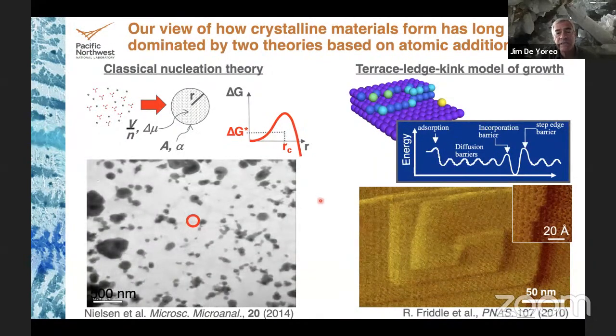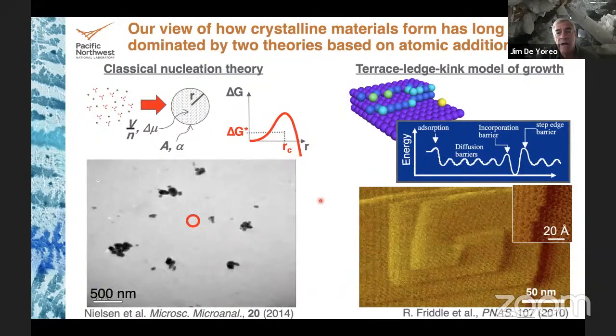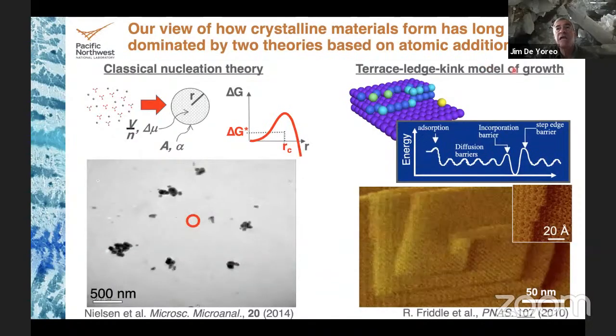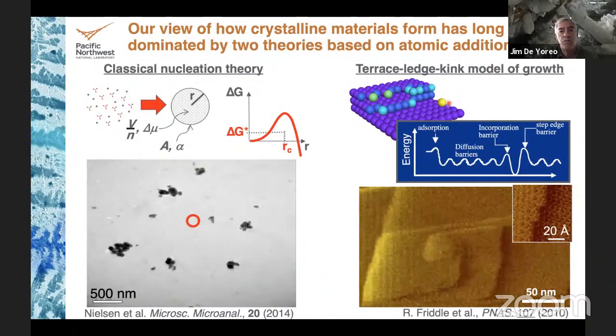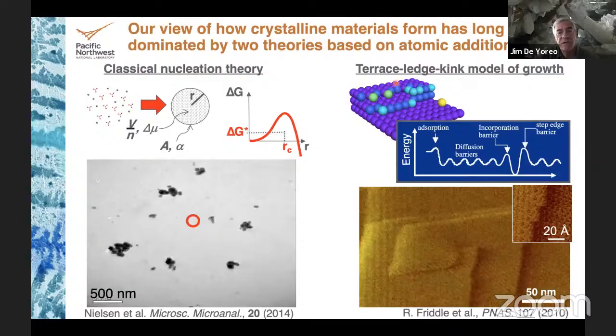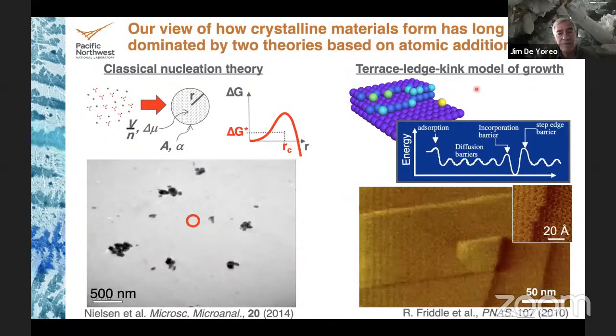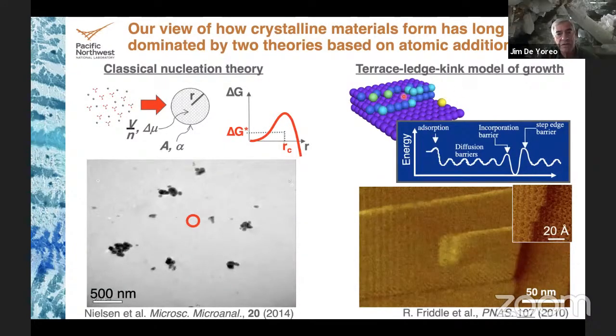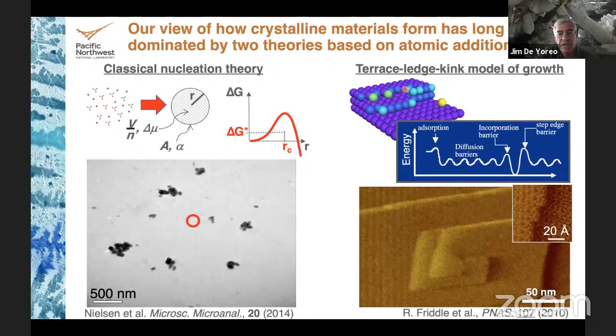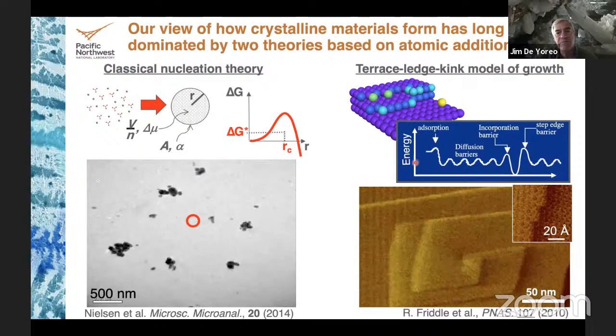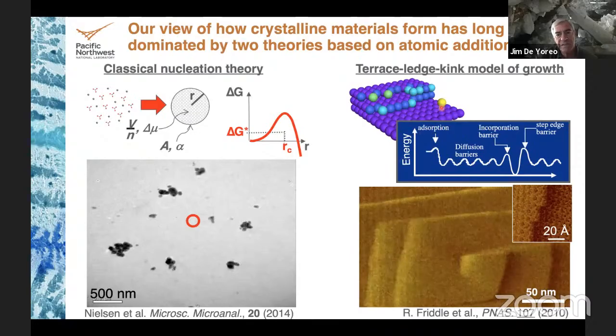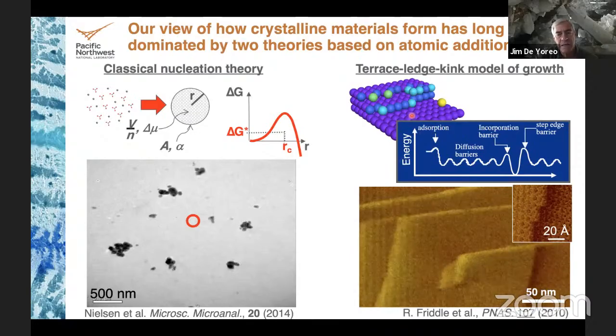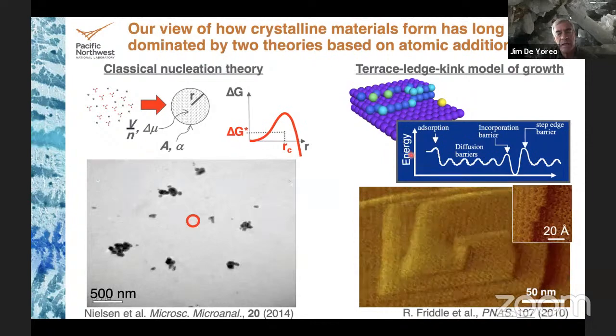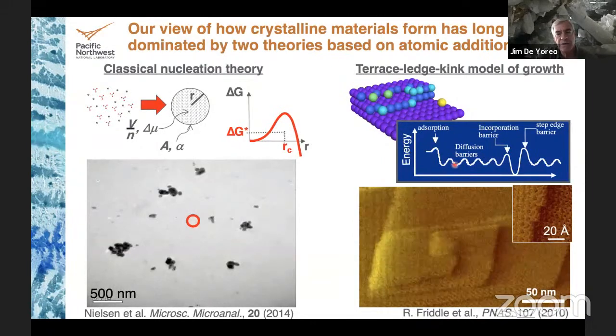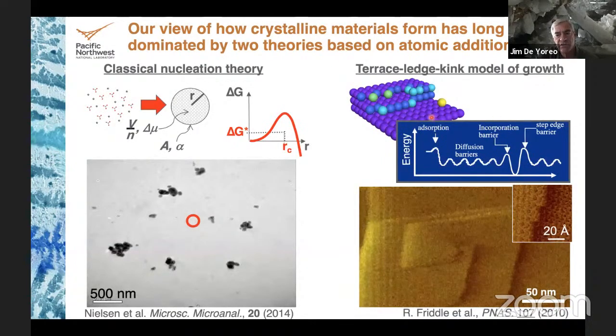After the nucleation process, the next stage is, of course, growth. And our understanding of growth has been dominated by the Terrace-Ledge-Kink model of growth, which says that surfaces of crystalline materials are covered in atomic steps. And the way they advance is the attachment of atoms or ions or molecules to the step edges. And this is not a free energy diagram. This is an energy diagram, meaning that what's dominating this process is kinetics, because the free energy barrier is gone. And now what we're doing is fighting the barriers to adsorption, diffusion, and incorporation at step edges.